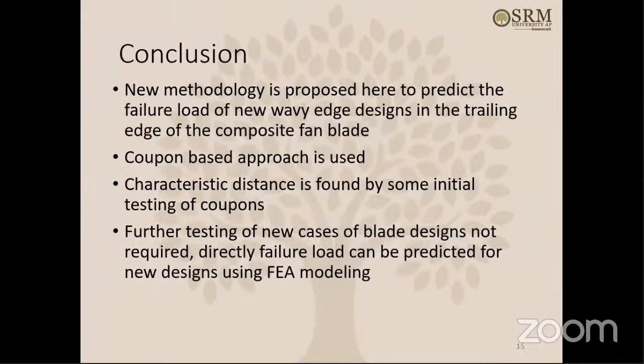So, conclusion: this is a new methodology that was proposed here to predict the failure load of new wavy edge specimens. How do you predict the failure load? For any new coupon, you can use the characteristic distance and predict the strain level. From the strain, you can find the failure strain. From the failure strain, you can find the failure load. So that's how you predict the failure load. This methodology is proposed here to predict the failure load of new wavy edge designs in the trailing edge. A coupon-based approach is used. The characteristic distance is found by some initial testing of coupons.